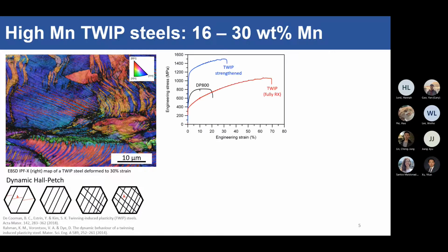So if you look at the tensile curve, TWIP steels have massive elongation here. That's because of the TWIP effect, giving it continuous hardening all along the tensile curve. So this is the fully recrystallized version. You can trade some of the elongation for strength, so you make it very strong, up more than 1 gigapascal strength. And what these TWIP steels are really good for is that it's absorbing energy. So if you think of energy absorbed as the area under the stress strain curve, this engineering should be doing true, but never mind. So these steels actually absorb a lot of energy when they deform, much, much more than the DP800 steels, which is the current energy absorbing steel in your cars right now.